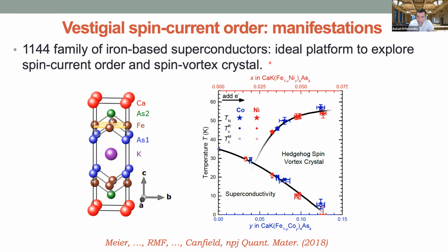Now this compound has a magnetic order, and because of this small symmetry-breaking field, it favors the phase that is compatible with this vestigial order, which is the spin vortex crystal. And this was observed experimentally. NMR showed that this is exactly the phase realized when you dope this compound. So this would offer a nice way to look for these Weyl points as well.